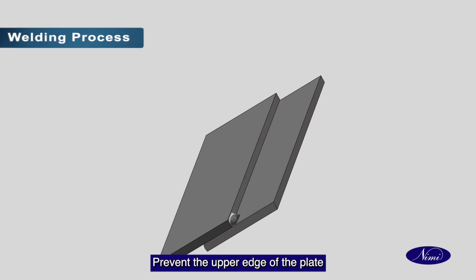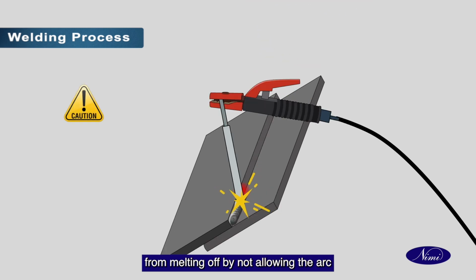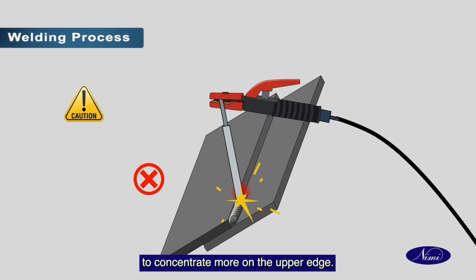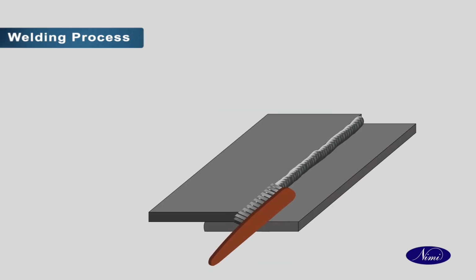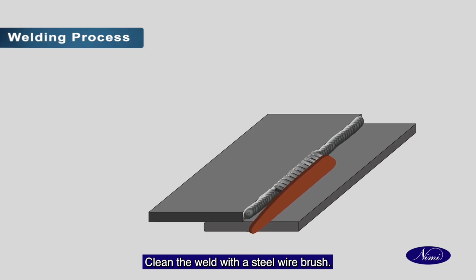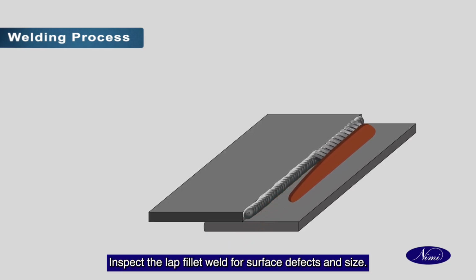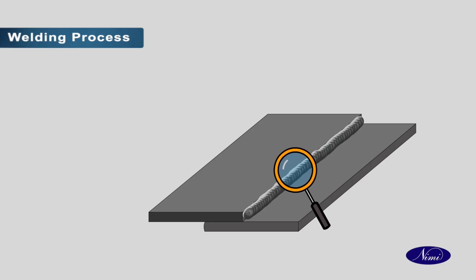Prevent the upper edge of the plate from melting off by not allowing the arc to concentrate more on the upper edge. Clean the weld with a steel wire brush. Inspect the lap fillet weld for surface defects and size.